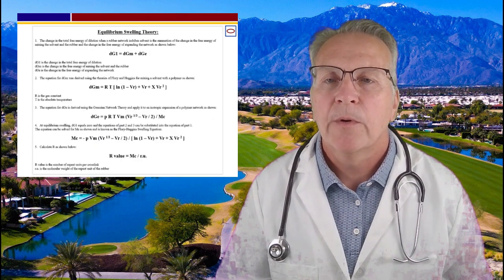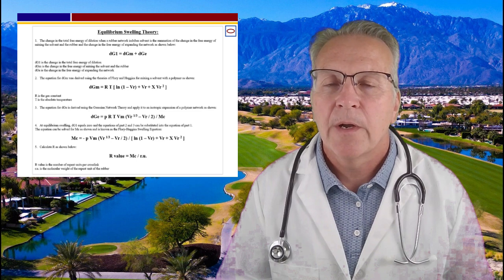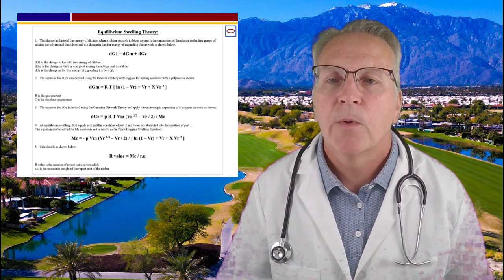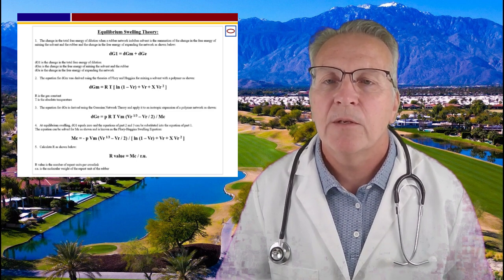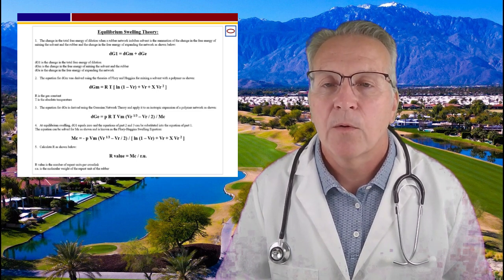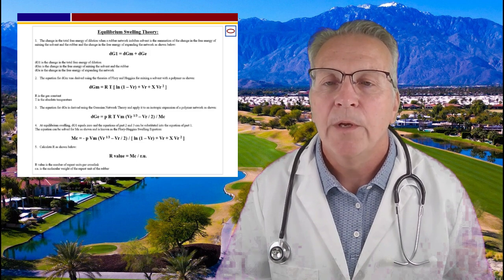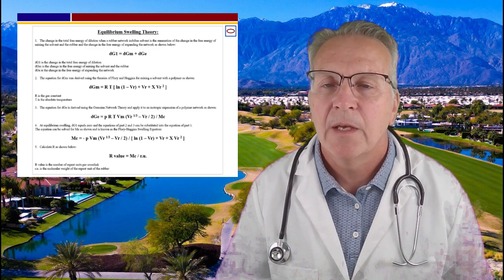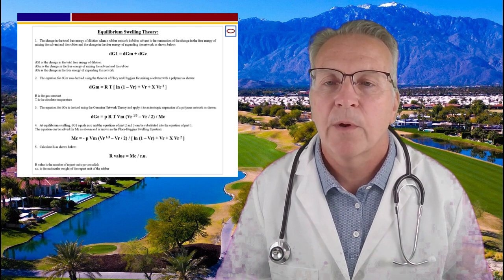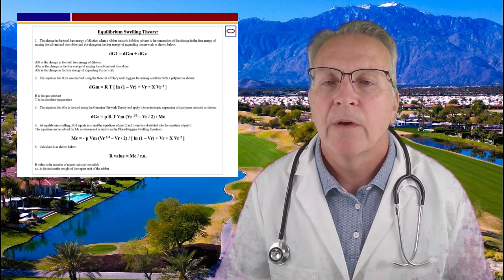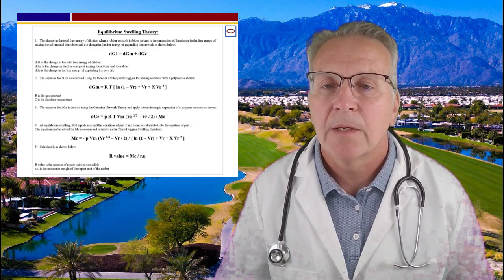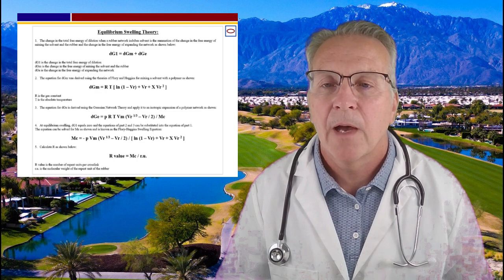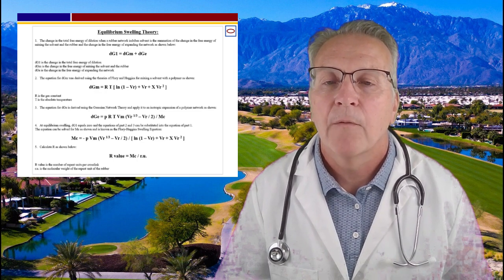The information on your screen shows the derivation of the Flory-Huggins Swelling Equation, which is used when a rubber network imbibes solvent, in which mixing and expansion creates the change in the total free energy of dilution. We use the Flory-Huggins theory of mixing and the Gaussian network theory for expansion, and at equilibrium swelling, we can solve for M sub c, or the molecular weight between crosslinks, and finally get an R value after dividing by the molecular weight of the repeat unit of the rubber.